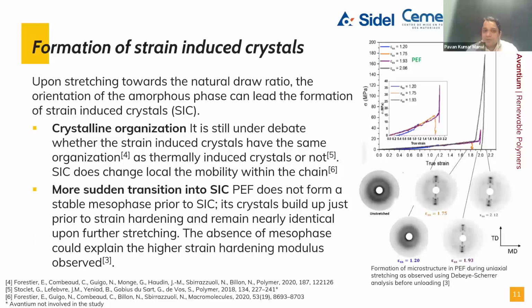This is not the case for PEF, but there is a sudden transition into stress-induced crystallization for PEF. So that we do not get more confused, please have a look at the data on the right side, the cycles from the WAXD analysis, the X-ray diffraction analysis. When the PEF is not stressed, it is completely halo. Then it is stressed up to some level, it is still halo, but instantly some intensity is diverted towards the equators.